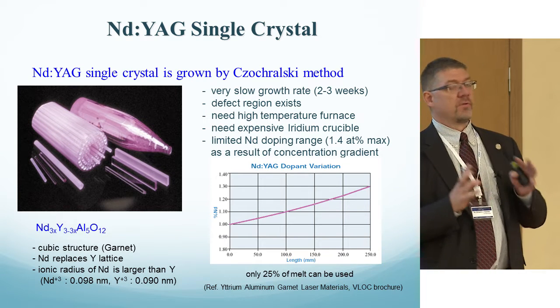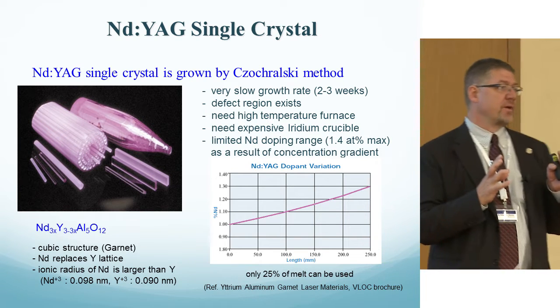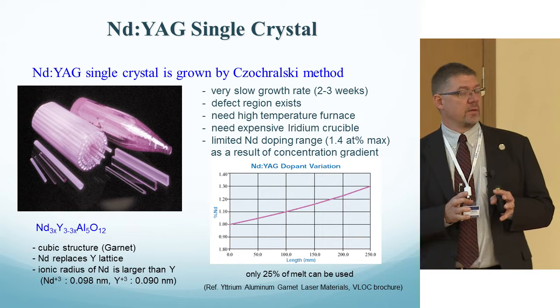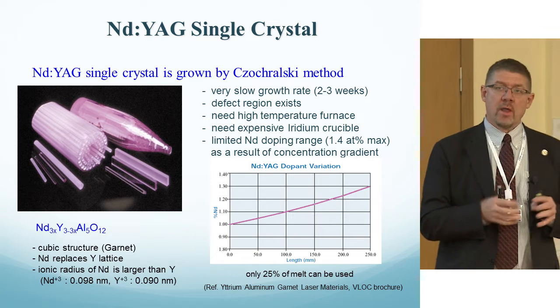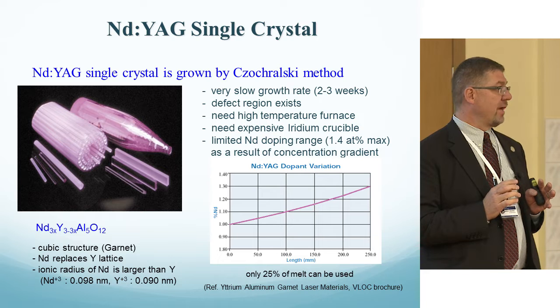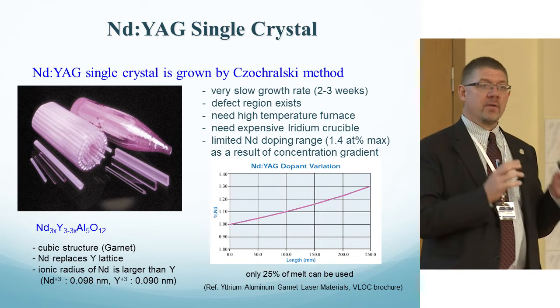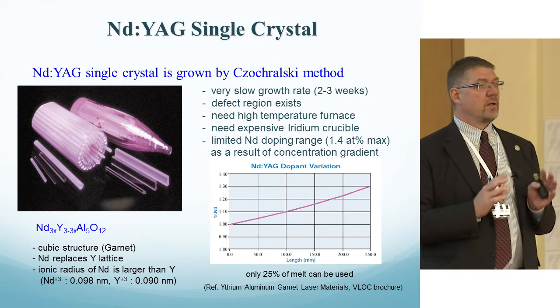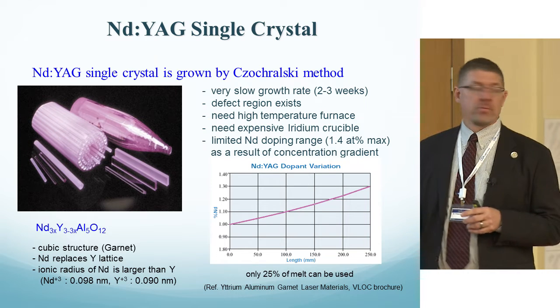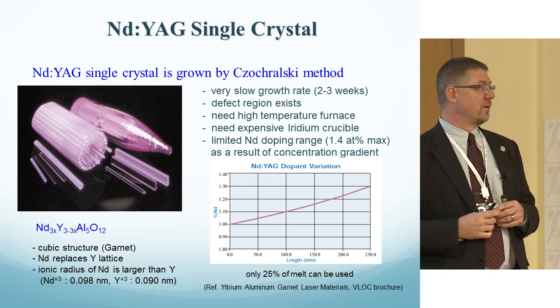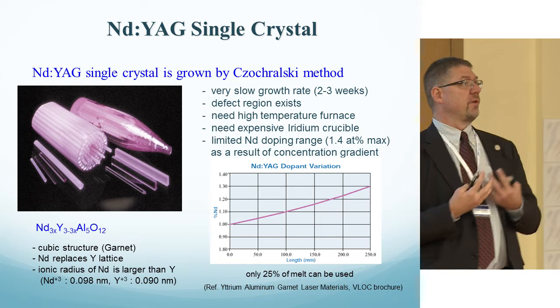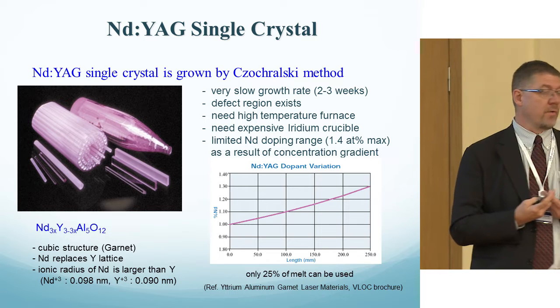So your furnaces, which are RF-based, have to have a tremendous amount of thermal stability. Something as small as a glitch in the power for 2 seconds, a lightning strike, the air conditioning shutting down in the room, all of those can turn this into a very pretty purple paperweight that can't be sold because it just sucks defects into it when the temperature starts to drop rapidly.